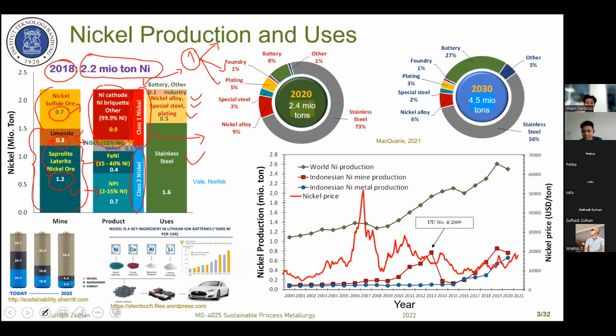And for nickel class 2, the utilization is limited to stainless steel. So we can use nickel class 2 only for stainless steel. It is not possible to use it, for example, for nickel alloy. If you want to use the nickel class 2 for nickel alloy, we should remove iron. We should convert, for example, to nickel matte, and then we remove iron to get the pure nickel, and after that we can use it for the nickel alloy.